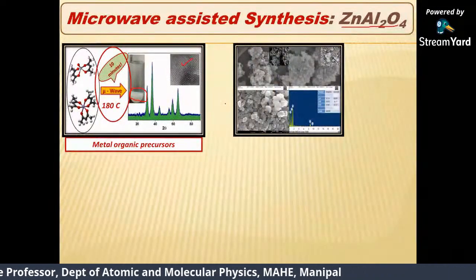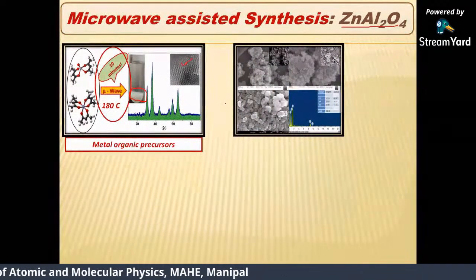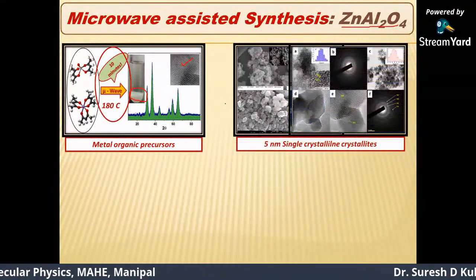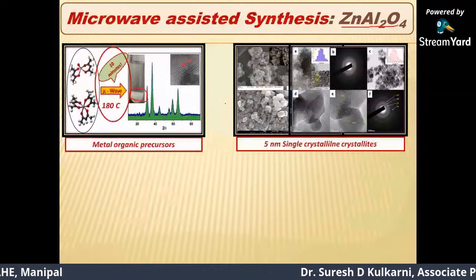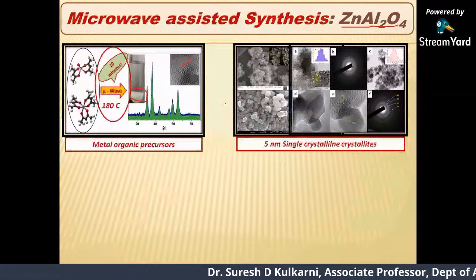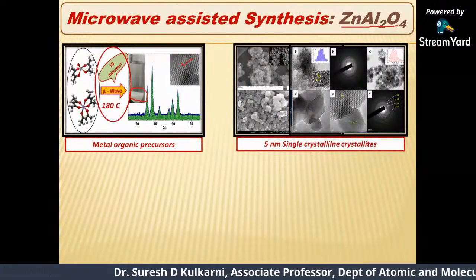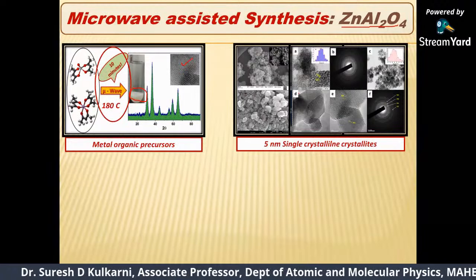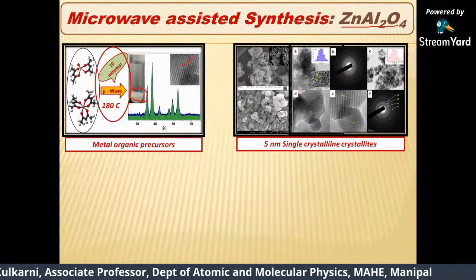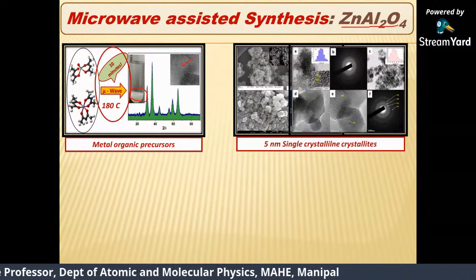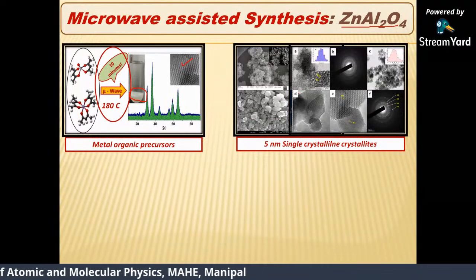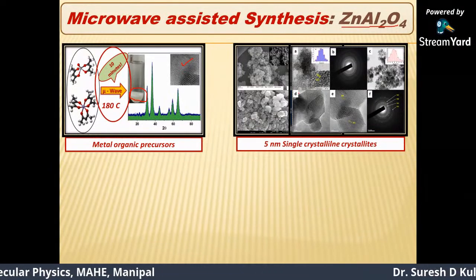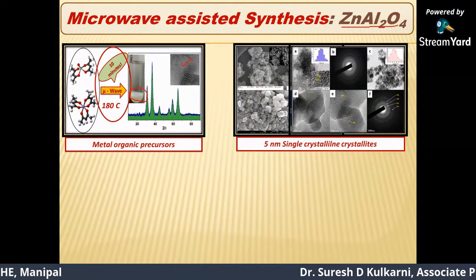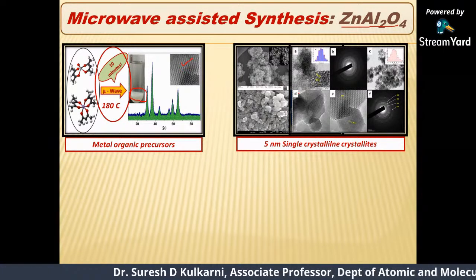We have done various characterizations to understand the particle size. All characterizations tell us that the material is nanocrystalline, and the size is about 5 nanometers. The particle size here is about 5 nanometers, and each crystallite is single crystalline. These are the important outcomes, and all that is achieved.